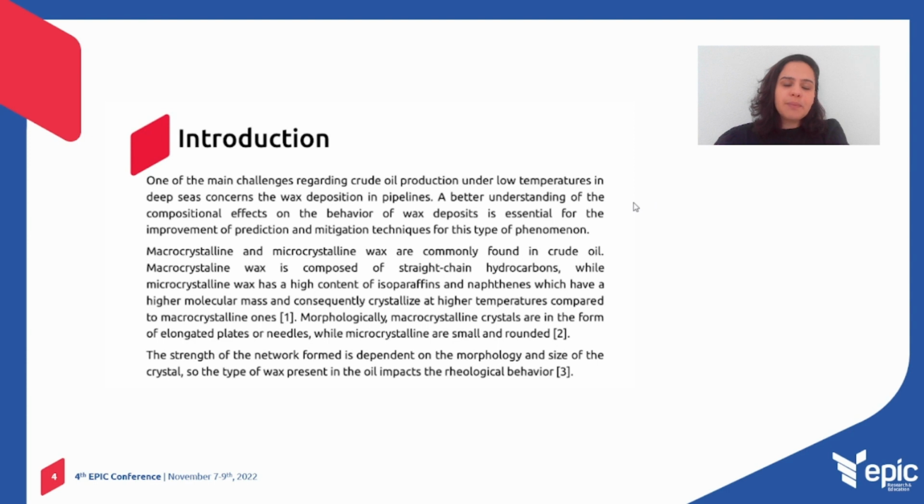So the morphology impacts the formation of different networks. The strength of the network formed depends on the morphology and the size of the crystals. So the type of wax present in the oil impacts the rheological behavior.